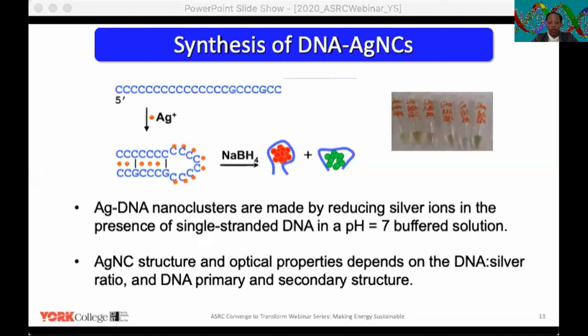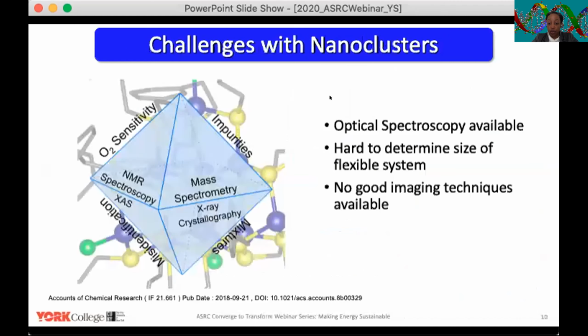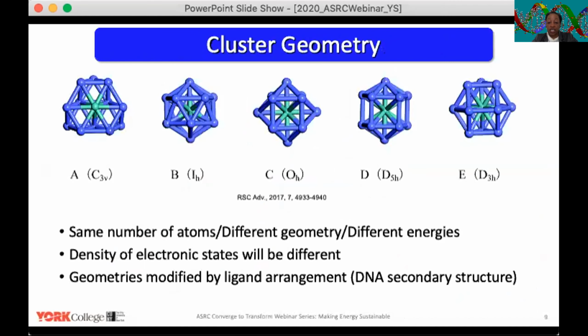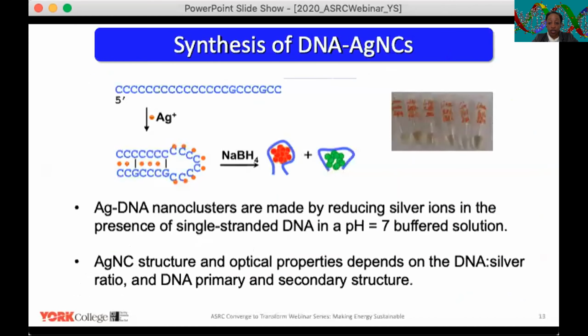Longer strands are, however, important to us because they facilitate the formation of those well-ordered silver nanoclusters that I mentioned on the previous slide. So we're looking mostly for very ordered structures of this nature. And so the longer strands enable that longer structure. And so the charge transport is due to the base pair sequence, the length, and the properties of the buffer solution. And so DNA can be seen as wiring for molecular electronics in this situation.